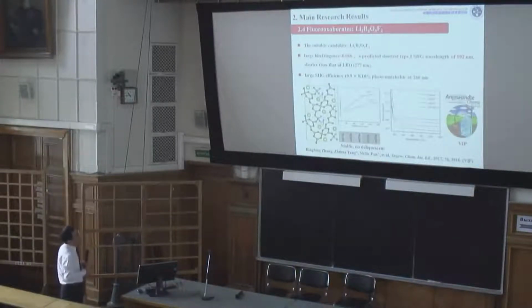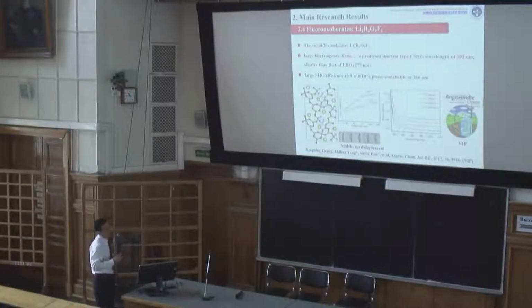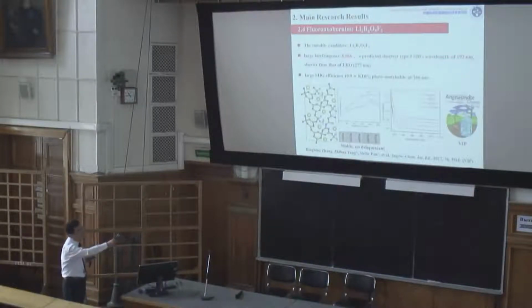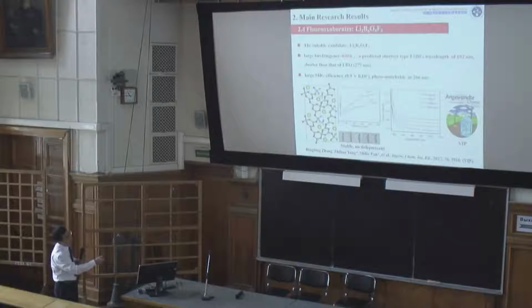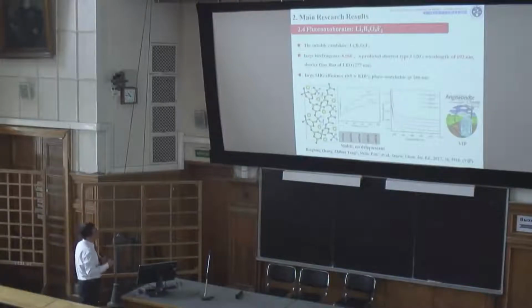For example, it has a suitable birefringence. In general, for nonlinear optical materials, the birefringence ranges from 0.04 to 0.1, so this birefringence is suitable. From the predicted birefringence, we can predict the shortest type 1 SHG wavelength is about 192. It means this material can output deep UV laser wavelengths below 200 nanometers. And this material also has a suitable SHG response, and is phase matchable at 266 nanometers.